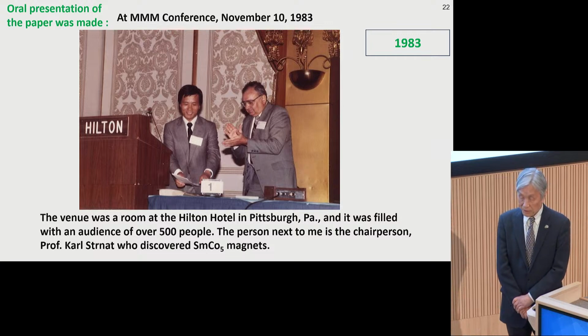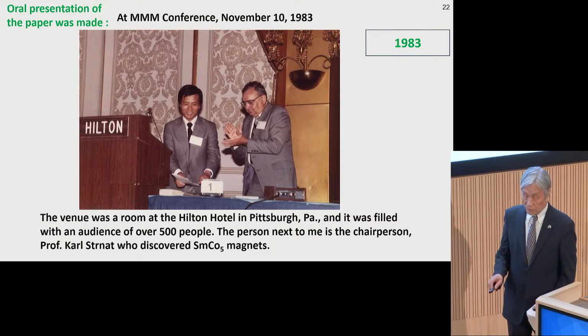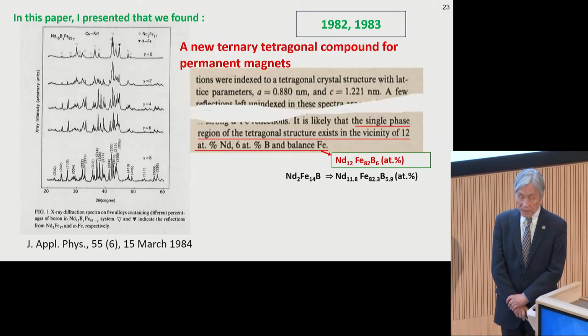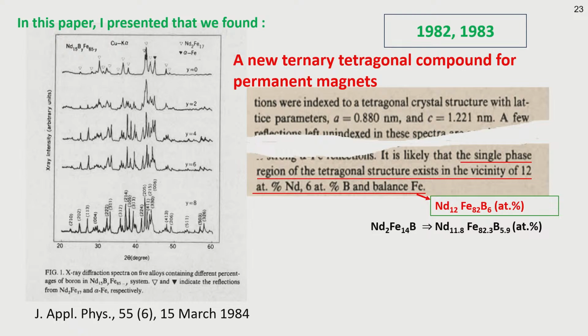The person next to me is the chairperson, Professor Karl Strnat, who discovered samarium cobalt magnets. In this paper, I presented that we found a new ternary tetragonal compound for permanent magnets. And tetragonal crystal structure with lattice parameters, we determined A, 0.880 nanometers, C, 1.221 nanometers. And we also determined the single phase region as neodymium 12, iron 82, boron 6 atomic percent.